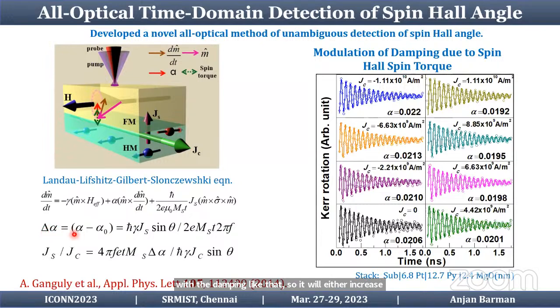So it will either increase or decrease the damping. And from the modulation of damping, we can find out Js over Jc, that is the spin Hall angle. So we did that experiment by measuring the damping and by varying the charge current density, the magnitude and the direction of that.